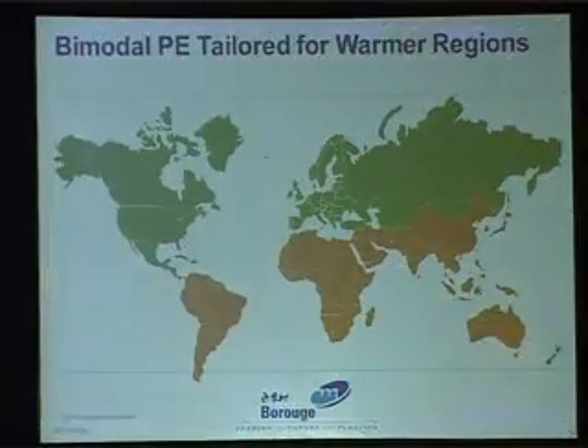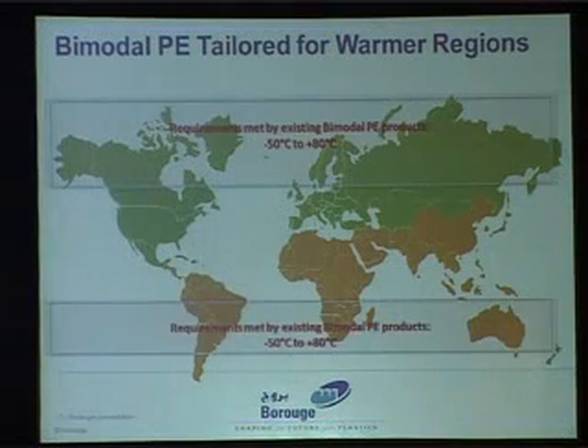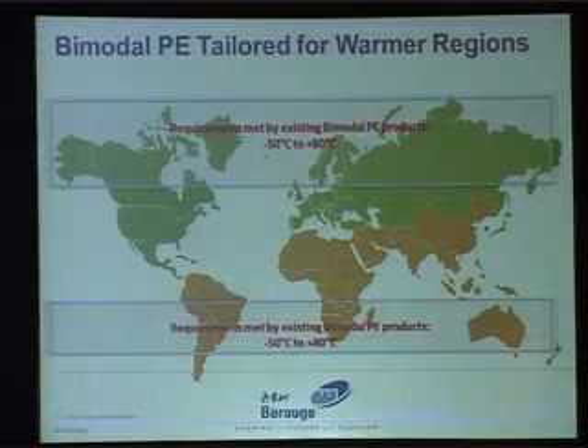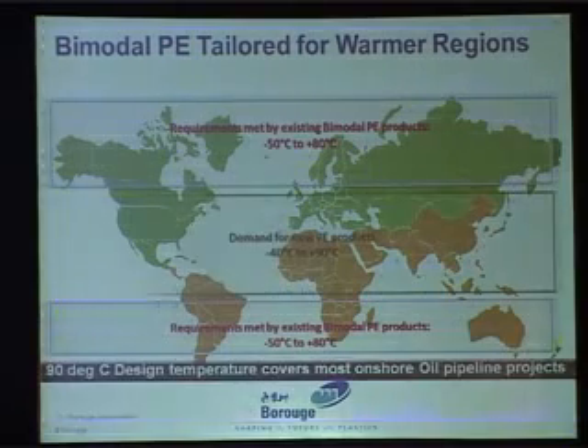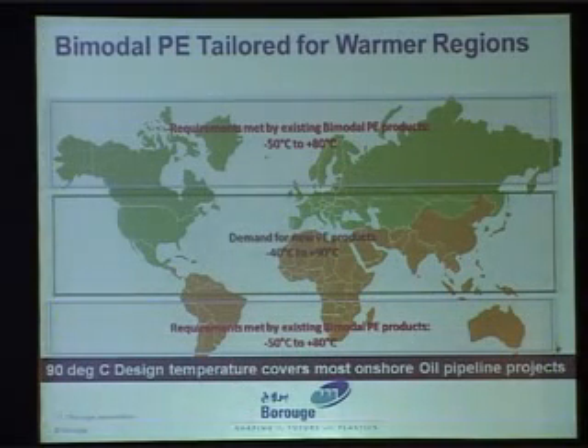The requirement for the colder regions of the globe is already taken care of by the existing 3LPE materials available, which can take care of -50 degrees centigrade to +80 degrees centigrade. But there is requirement for the equatorial region or the warmer countries for onshore pipeline coating, which can handle at least +90 degrees centigrade, which will cover 90% of the onshore oil pipelines.